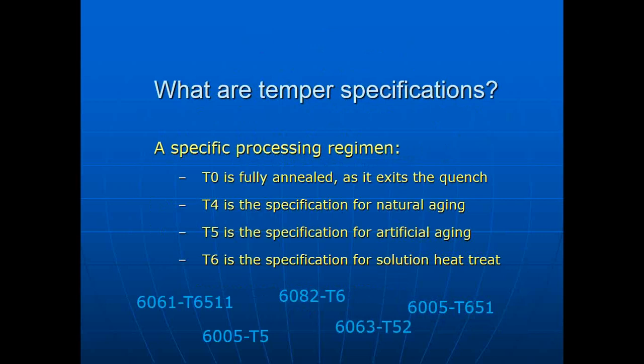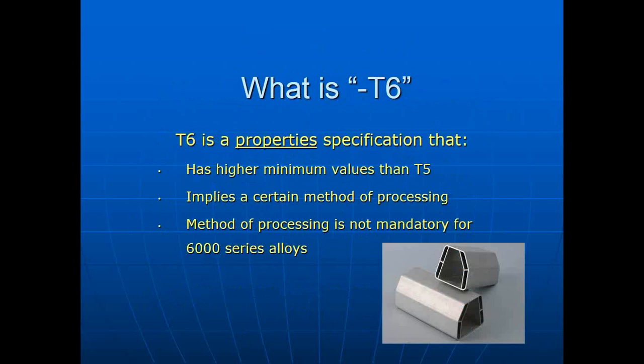T6 is the specification for solution heat treat. That, in all alloys except 6000, requires a secondary step for solution heat treat. With the 6000 series of alloys, T6 becomes a properties specification. The values for strength and hardness are higher than for T5, and there's an implied method of processing.